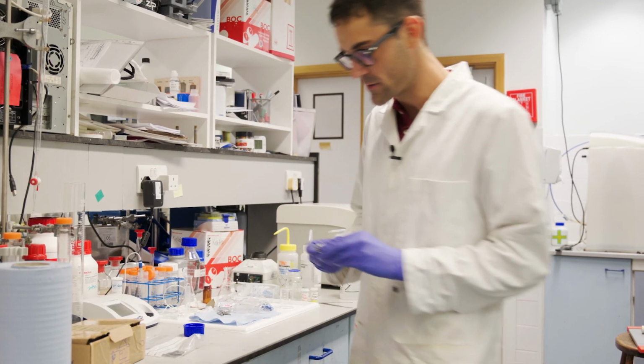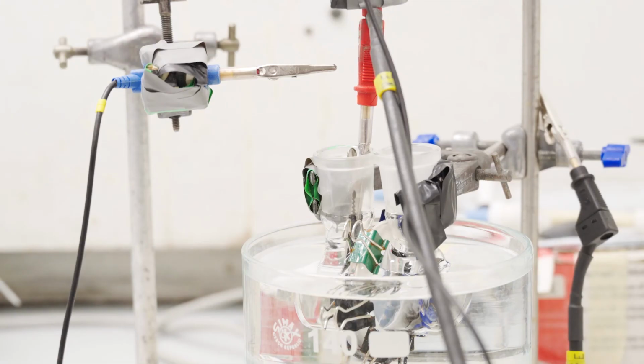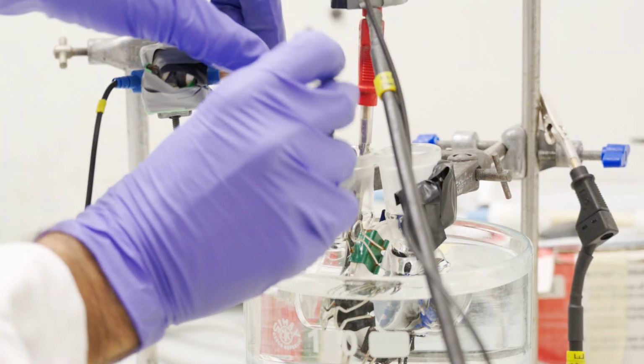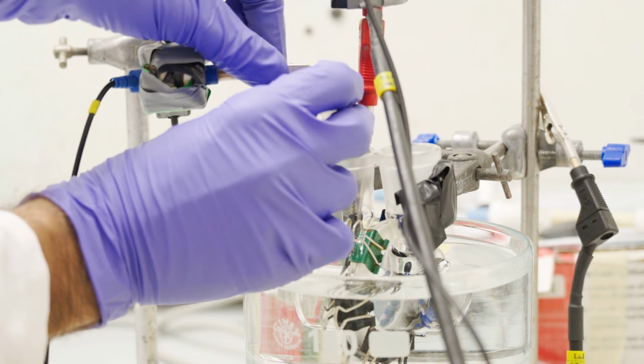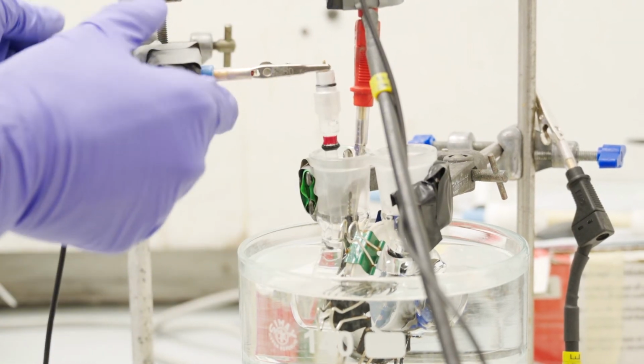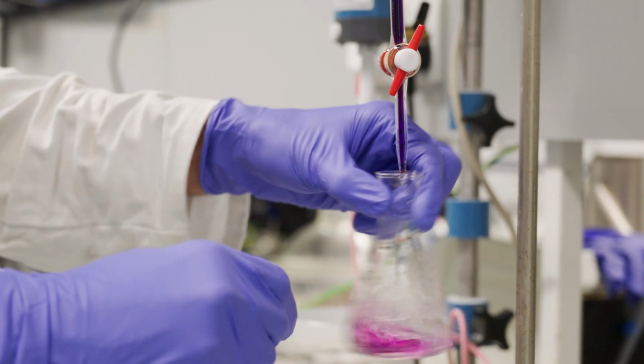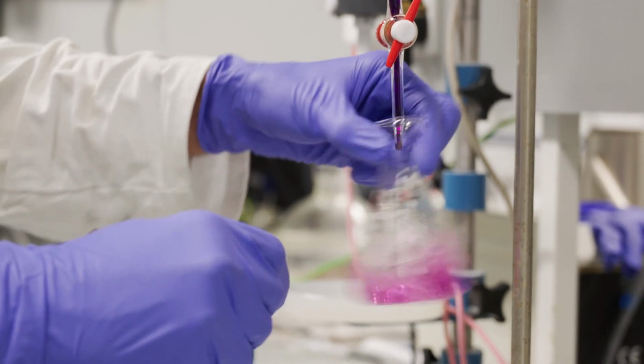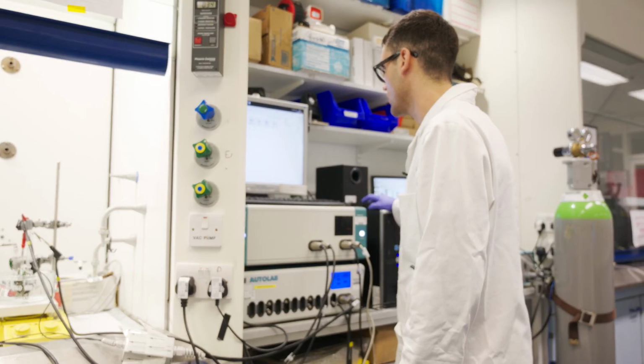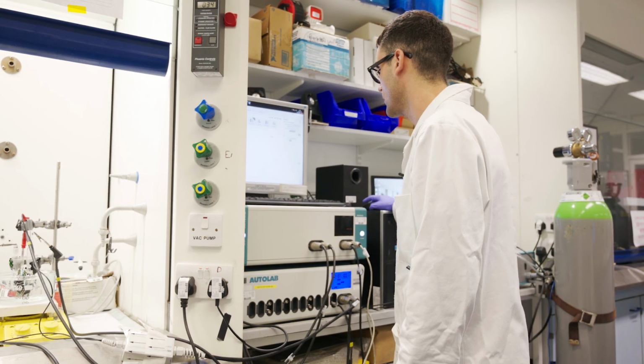We found that boron-doped diamond is a very suitable catalyst for this reaction and this project, and it meets all of the requirements more or less that were set to us for the water oxidation part. That was more of the step forward that I was proud of. Not only found a material that meets the requirements for the project, but that we were able to show that we can actually get this reaction to work at the level that we wanted to work, at the performance. That was the cool thing.